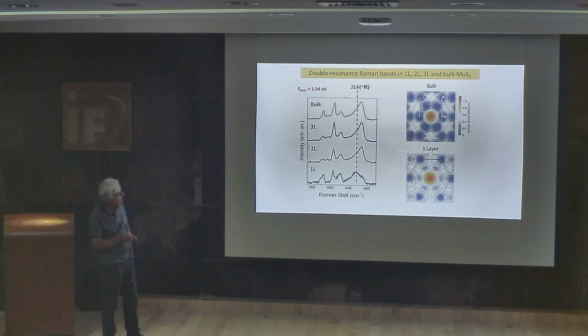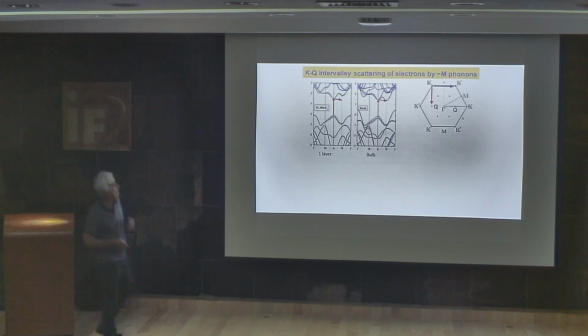the Q point. Now, in the case of bulk, 2 layers and 3 layers, we have 2 different kinds of valleys. Not only valleys at the K point, but we have valleys at those points, Q points, that are between K and gamma. And what we could see is that scattering from K to Q, for bulk, is possible because we have here the minimum of the band. Then we have this process from K to Q. That's possible in bulk and 2 layers. But in the case of 1 layer, we cannot have the scattering from K to Q because the valley here is not deep enough.